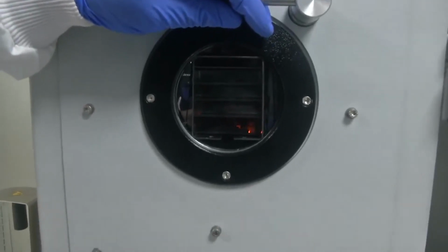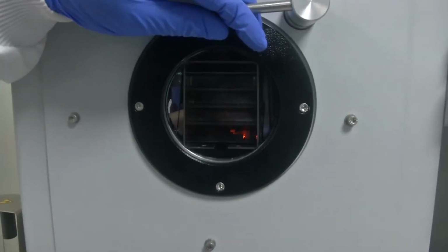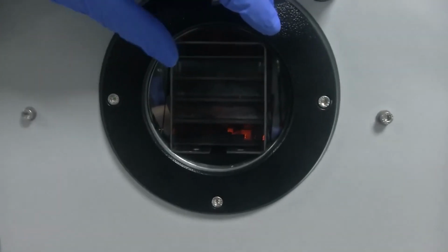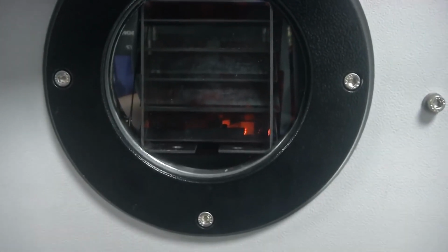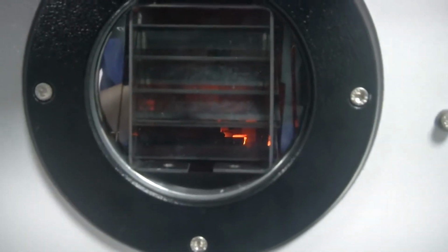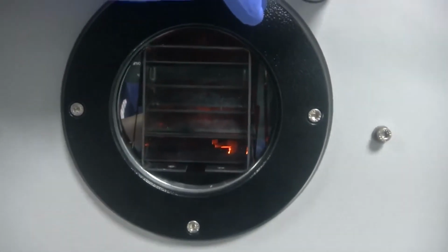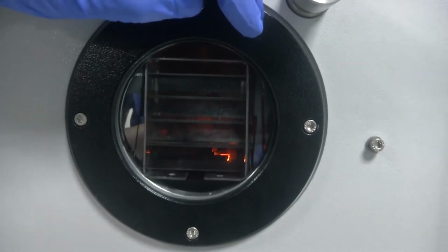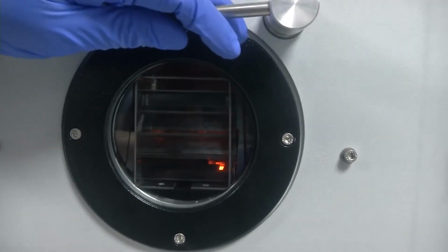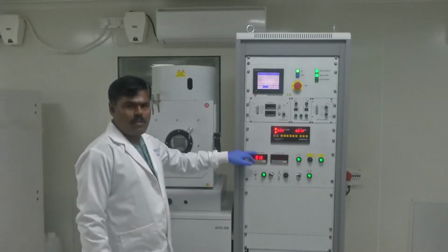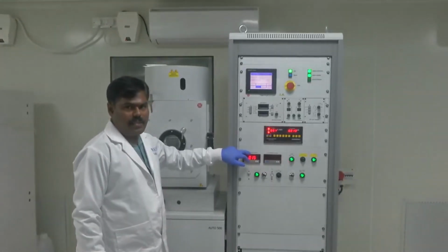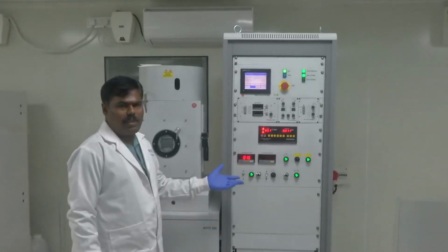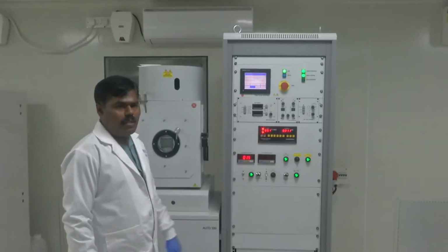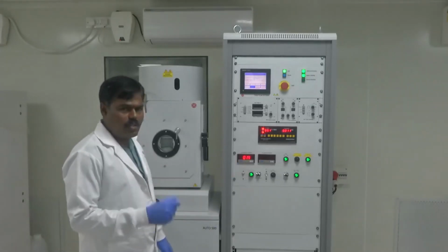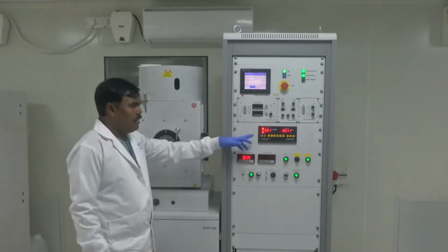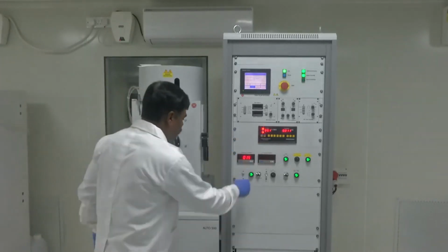You observe inside the chamber, the filament is glowing and the material is going to melt. So before that, open the shutter and switch on the rotary drive. Before doing the deposition, pre-melting is required. Pre-melting means you apply low current for 1 or 2 minutes. After that, you have to increase the current to do the coating.